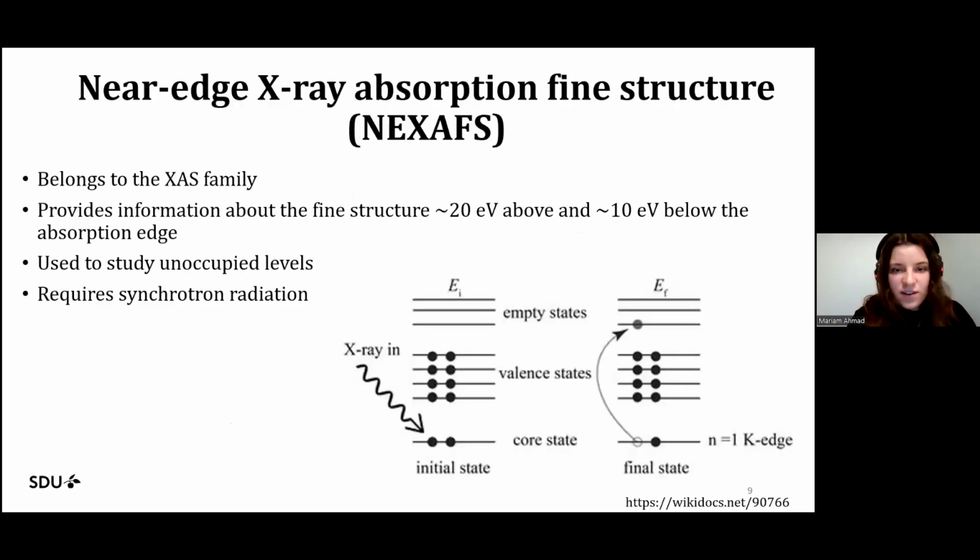Another X-ray-based characterization technique that was used in this study is near-edge X-ray absorption fine structure, or NEXAFS for short, and it is an X-ray absorption spectroscopy technique. As the name indicates, it provides information about the fine structure close to the absorption edge. In this technique, you also have a surface that is hit by some incoming X-rays, but in this case, the photon energy of the X-rays is either equal to or slightly below the vacuum energy.